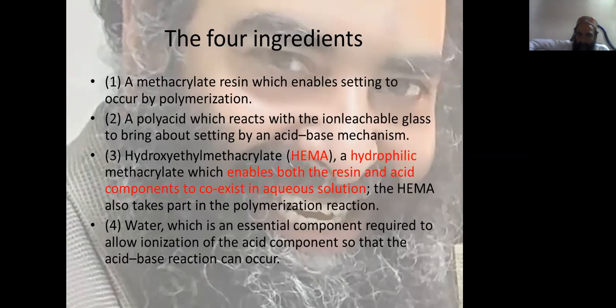Three, HEMA, hydroxyethyl methacrylate, which is a hydrophilic methacrylate and enables both the resin and acid component to coexist in aqueous solution. HEMA also takes part in the polymerization reaction. And four, water. Water is an essential component required to allow ionization of the acid component so that the acid-base reaction can occur.